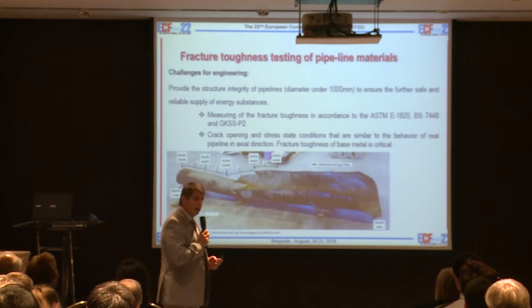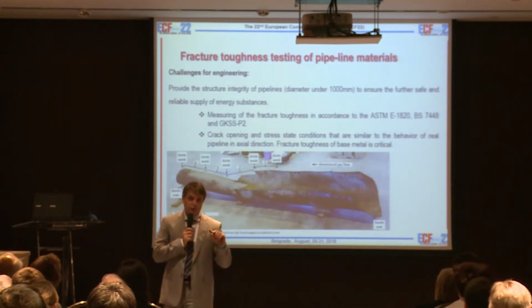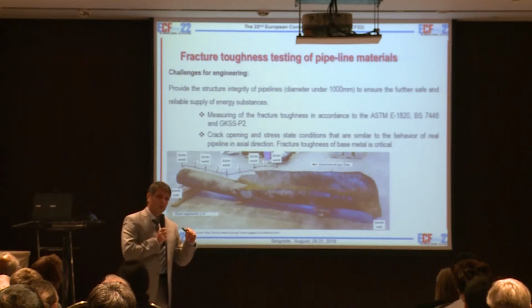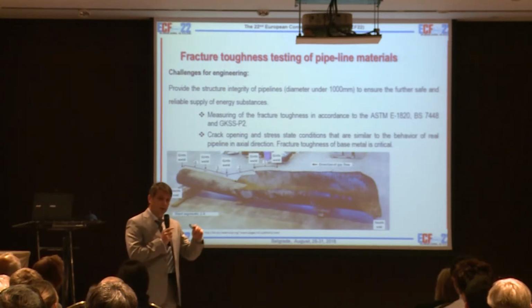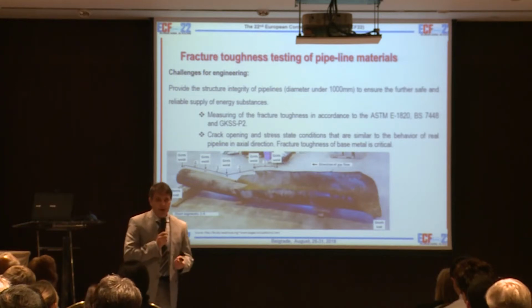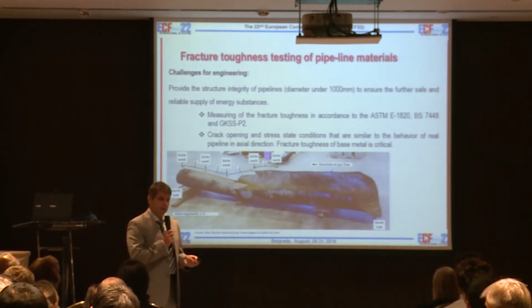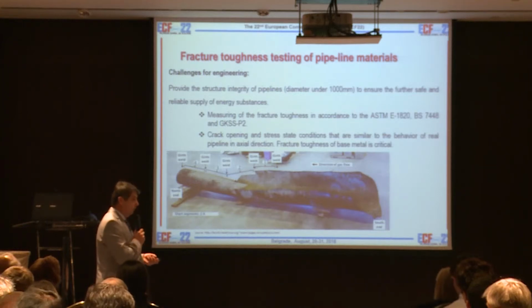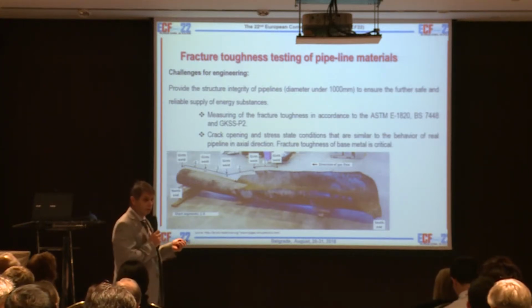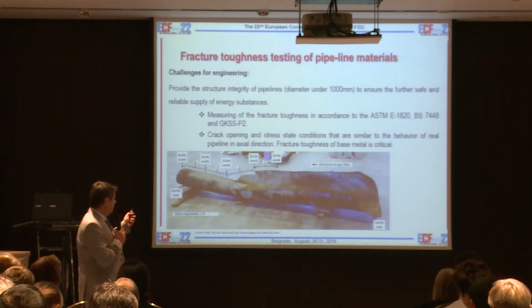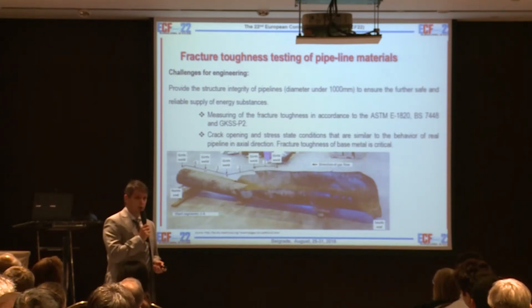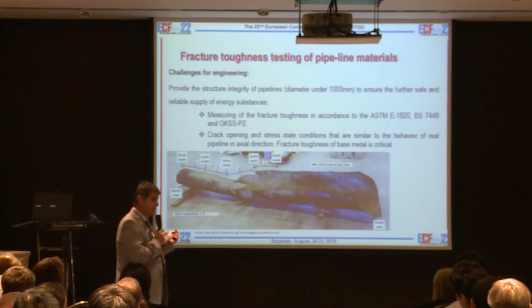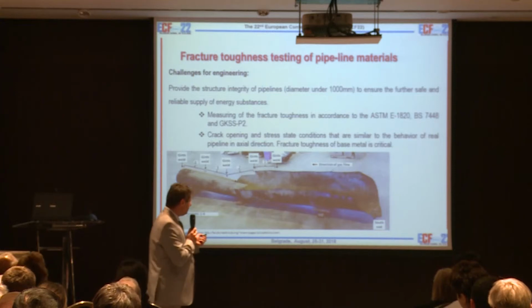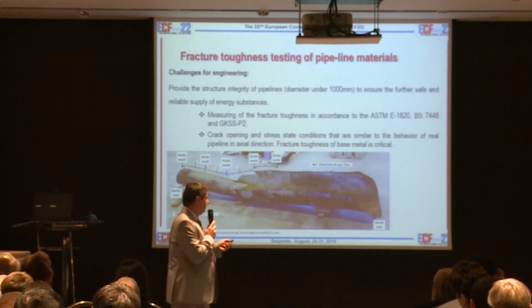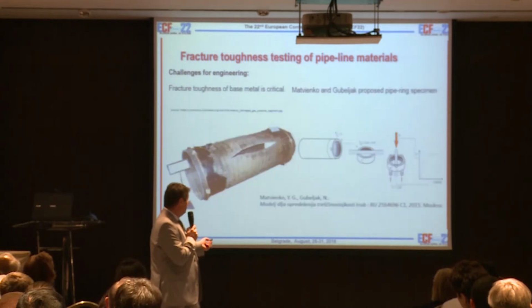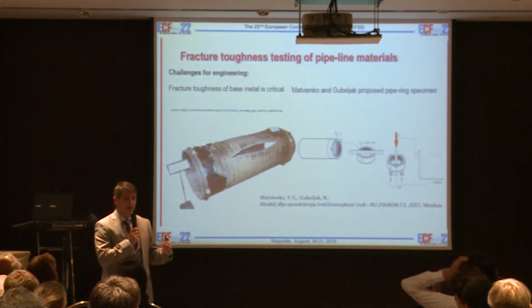So, the problem with pipes is that very often they want to reduce the material weight and they have low thickness, so small thickness relative to diameter, and in this case it's very hard to make a standard specimen from this pipeline wall. We know and use different procedures for fracture toughness determination. One of these is the GKSS P2 procedure, published more than 20 years ago. But we are also working now in all these standards, trying to find an alternative method.